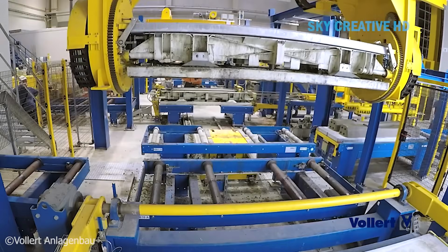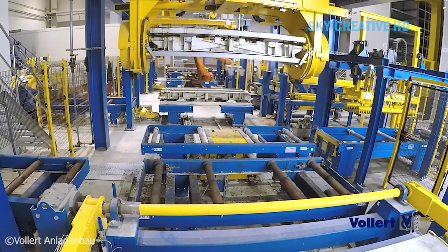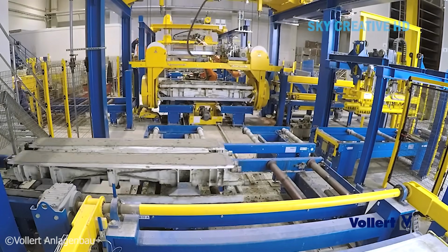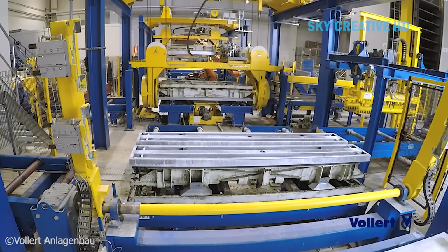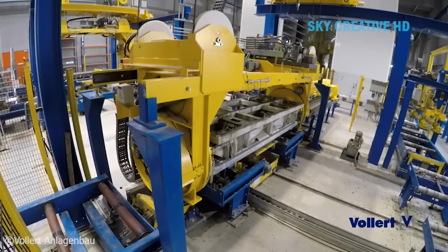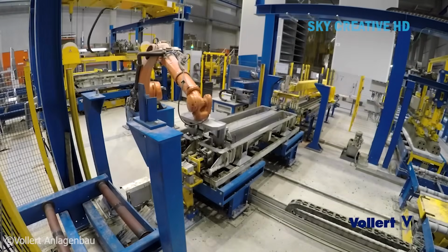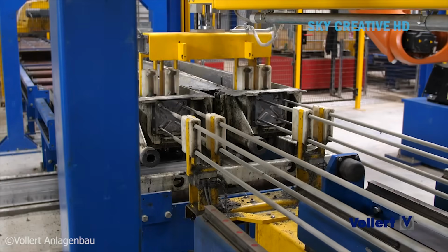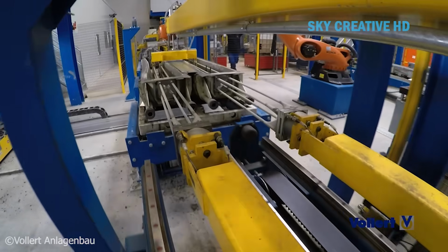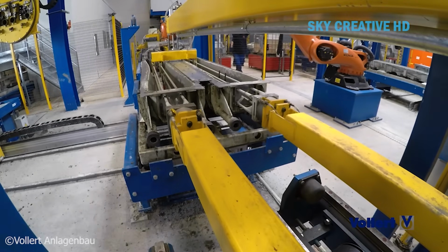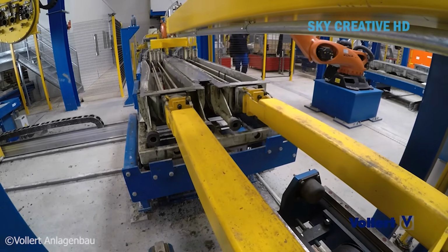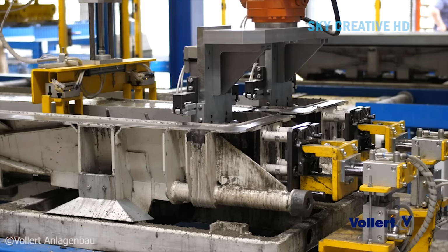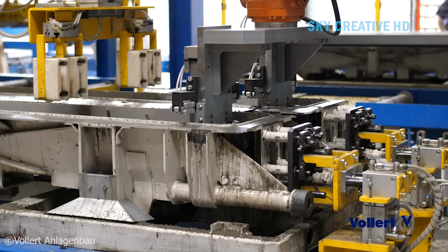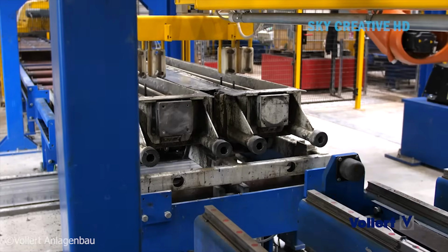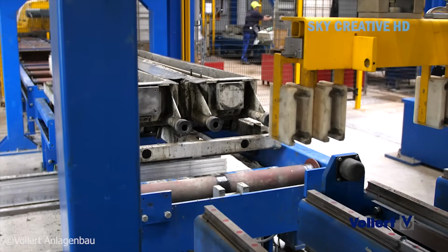This specialized mixture includes Portland cement, precisely graded aggregates, and chemical admixtures that control everything from setting time to ultimate strength. The concrete achieves a compressive strength of over 8,000 pounds per square inch. That's strong enough to support a loaded freight train traveling at 80 miles per hour. And watch as the automated batching system measures each component to tolerances of plus or minus 1%. The mixing process itself is a marvel of precision timing. High-intensity mixers blend the materials for exactly 90 seconds, not a second more or less.